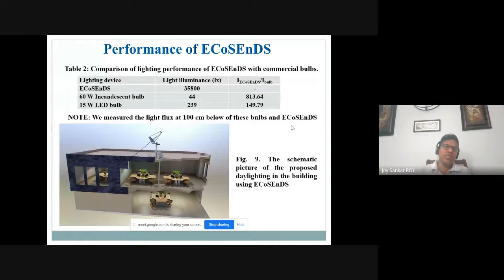Anyway, I measured this just to propose our system, to understand how good it is, and whether we can use it for commercial purposes or not. So we did some experiments. We compared the light intensity with the normal light intensity available in the market, like LED or a normal incandescent bulb. So I measured the luminous flux, basically light illuminance. From the ECoSEnDS we are getting 35,800, but when we use a 60 watt incandescent bulb that we use in our households, basically only 44. If we use a 15 watt LED bulb, which everyone knows is quite good compared to an incandescent bulb,